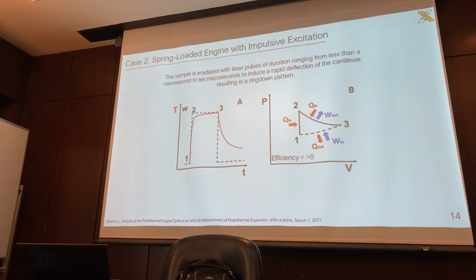So imagine if my left hand is the sample, my right hand is the probe. It's fully expanded, and then the sample collapses. Well, you have a gap of time between the time that the probe can return to the sample. And so it transfers potential energy and converts that potential energy into kinetic energy. And so now we're doing work on the sample itself. And that's the process that you're seeing from 3 and 4. Of course, we're getting a lot of thermal energy out, which is our Q out there.